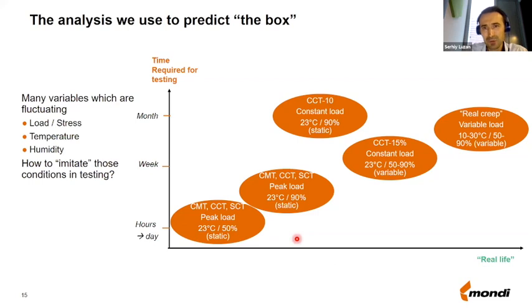Therefore, the suppliers and producers of paper were looking for other ways to look at paper resistance. And one of the tests which was developed was the so-called CCT test, where the paper was subjected to a constant load at 90% relative humidity and you measure how long the paper resists this load. And normally you would report the load which paper can hold for 10 days. And this test, of course, shows you a bit better the link between real life conditions and the testing. But then the next step was the so-called CCT 15% test, where instead of constant relative humidity, the relative humidity was changing from 50 to 90%. And therefore, this test was even closer to real life.